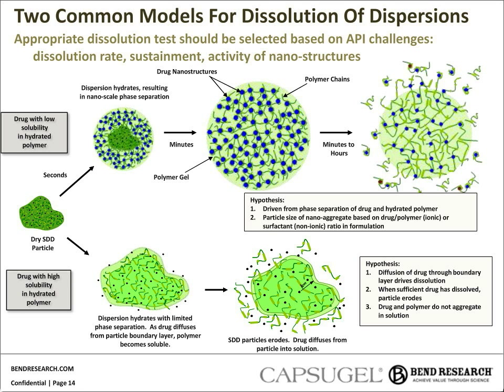As those nanostructures are created and composed, the drug particle continues to swell and starts to break up. It releases these nanostructures, which allows the free and the micelle drug concentrations to be rapidly replenished. So it is kind of driven from a phase separation of the drug with the hydrated polymer. And particle size doesn't tend to be a strong determinant of performance in this case because of the rapid nature of these interactions.